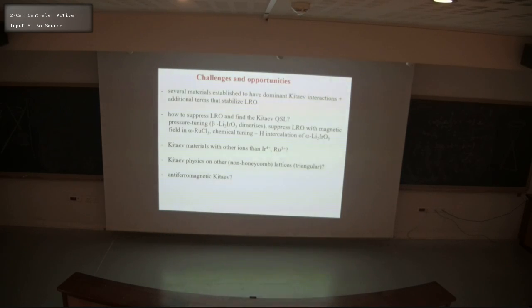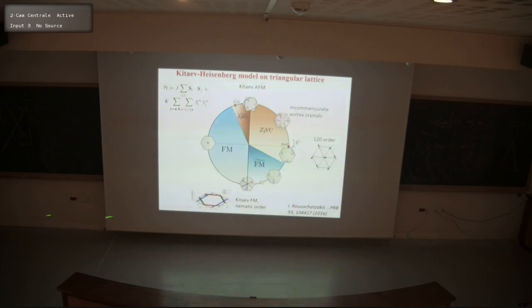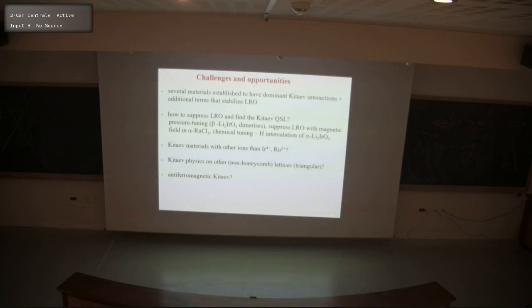Also, another issue maybe to bear in mind is that the Kitaev model is only one representative of a wider class of systems with bond directional anisotropies that can stabilize quite unusual cooperative magnetic phases. And we've seen on the honeycomb lattice how counter-rotating spiral order can come about, but also there are various predictions for triangular lattices with quite complex phase diagrams with nematic order or incommensurate phases that can be described as vortex crystals and so on. And certainly it will be interesting experimentally to look for some of this.